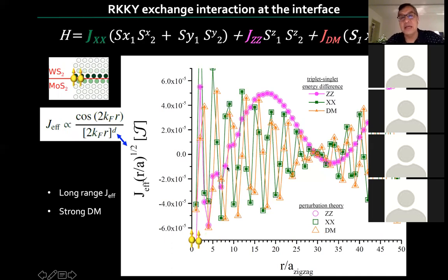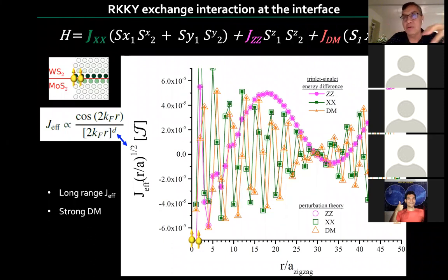The other thing that is interesting is that the effective confinement of the wave functions gives you a rather long tail of this interaction. So the impurities that are close to these interfaces will interact with each other over very, very long distances, which will give rise to interesting physics. And as I mentioned, they have a strong Dzyaloshinskii-Moriya interaction. So if you put impurities in a system that sits around this interface, the interactions will be relatively long range. They will have a strong non-collinear term.